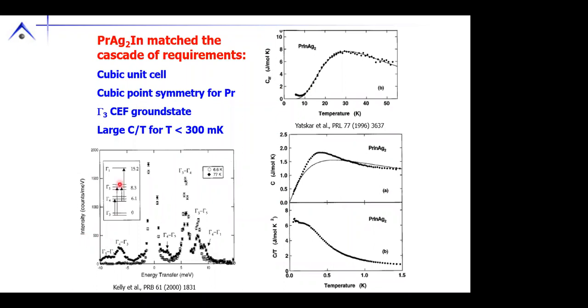So we were able to reproduce her inelastic neutron scattering. We see gamma-3 is the ground state separated by about 6.1 meV. We can take this cascade of CEF splitting and fit our specific heat data to it very well at high temperatures. But at low temperature, something happens. If we look more carefully, we see specific heat coming up, saturating, and then going linearly to zero through 0, 0. So if we plot C over T versus temperature, we see the linear specific heat rising and saturating at 6 joules per mole K squared. That is a very, very large linear specific heat.